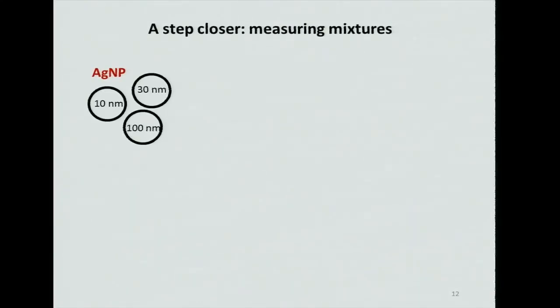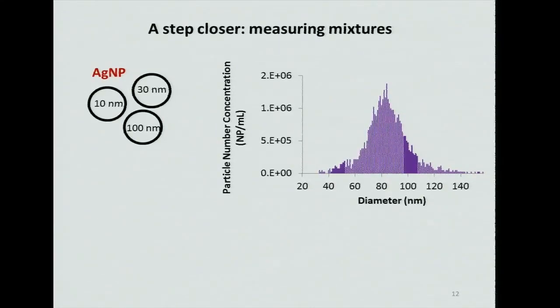The next step was to work with slightly more complex samples. So for this, we used 3 sizes of silver nanoparticles. We first ran them in SP-ICP-MS, where we got a very nice size distribution. You may wonder what is wrong with this graph. It's representing all 3 sizes. But what we're not able to see is the exact composition of each of these sizes.